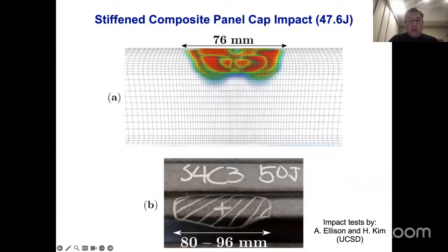Here, our experimental colleagues are showing the extent of the delaminations that they are able to capture through CT scanning, and it's about 80 to 90 millimeters. In our calculations, we're getting almost 80 millimeters. So here, what we're doing is we're taking all of the contours of the cohesive damage variable and plotting it on each interface, getting this very nice composite image. And you can see that the delaminations are curving very nicely around the curved interfaces.